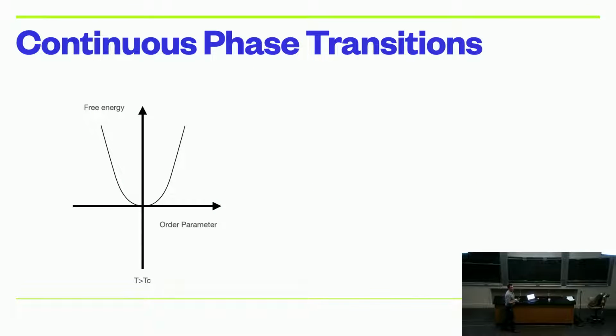Okay, so how do we describe what happens across a phase transition? Well, we often draw an energy landscape. And here's what I have as just a parabola where I have what we call an order parameter. This characterizes what the spins want to do in the case of the ferromagnet. So the order parameter is a measure of what those interactions are kind of driving. In the case of a ferromagnet, it's magnetization. So it's like what the magnetic moment is of these spins aligning together. And that order parameter, we can assign a value to it, 0, for example. And as you go to a finite value, it goes to a higher energy. So obviously, for this particular case, the whole system wants to have 0 magnetization. So that's what we call just an ordinary paramagnet.